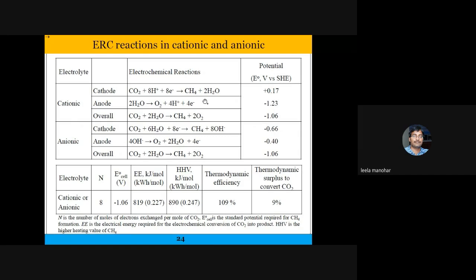Most people right now are using anionic electrolyte because the main competitive reaction is hydrogen evolution, right? When hydrogen forms, protons and electrons combine and hydrogen will be there. Suppressing that competitive reaction is key. In most of the recent papers we see carbon dioxide reduction using anionic electrolyte is more significant, because the hydrogen evolution is almost less than 2 to 5%, and they are getting selective formation of the products.